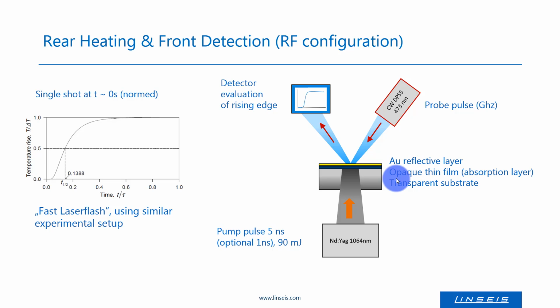In the end, the experimental data looks very similar to the standard laser flash, with an increasing edge, which we use for the evaluation of the thermal diffusivity of the sample. Only the time scale is different.